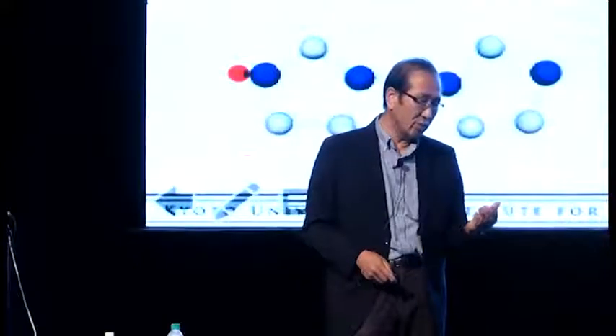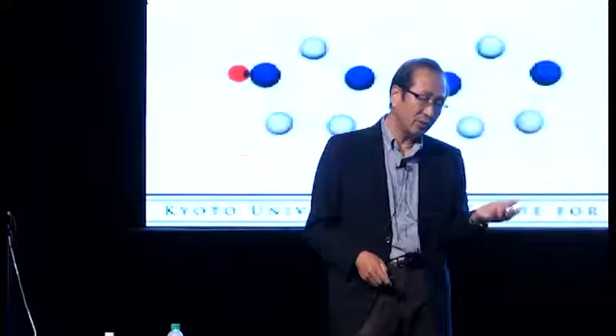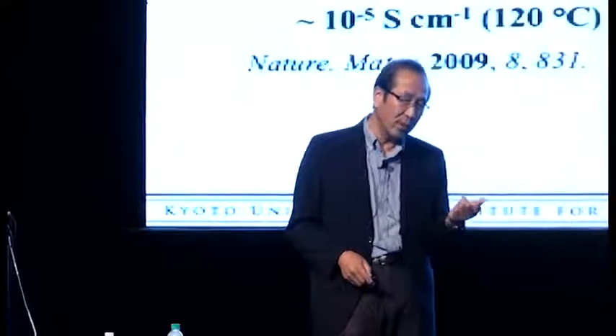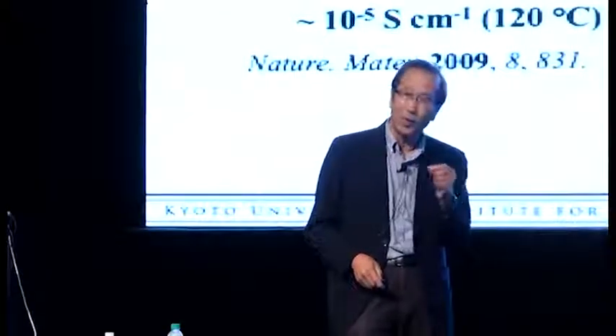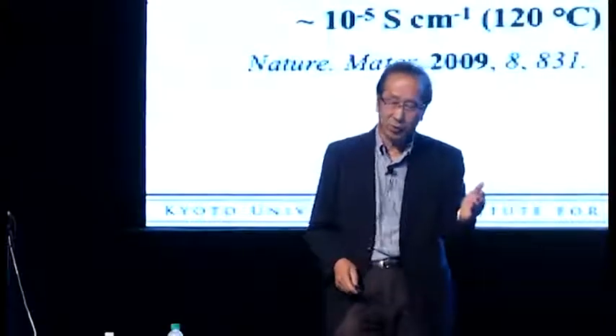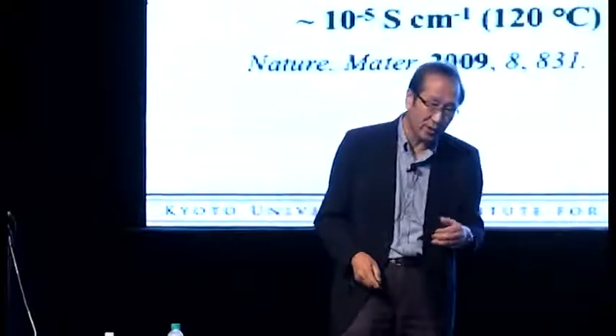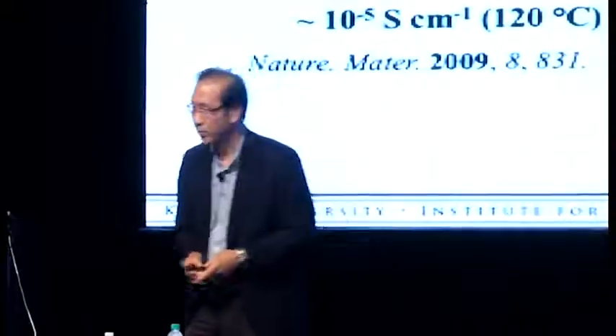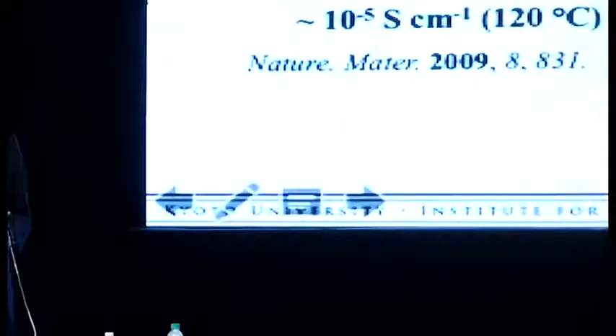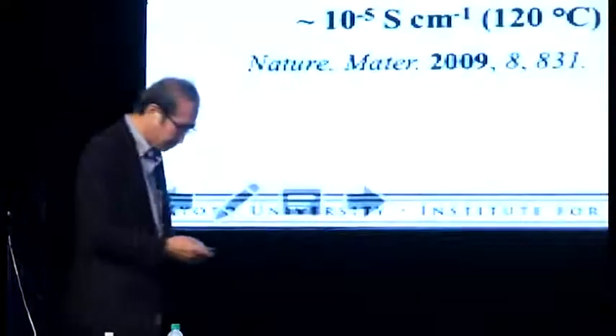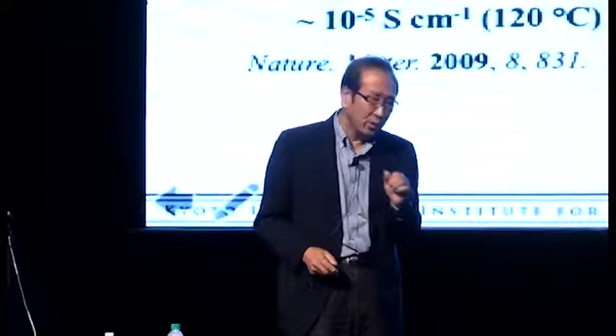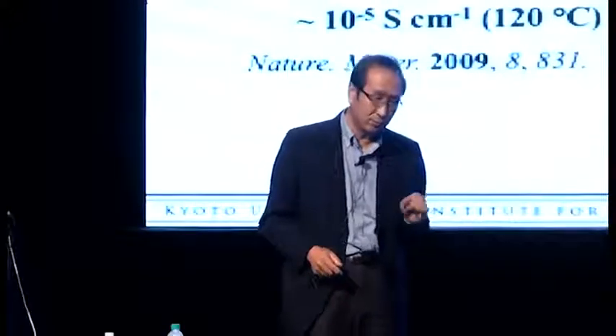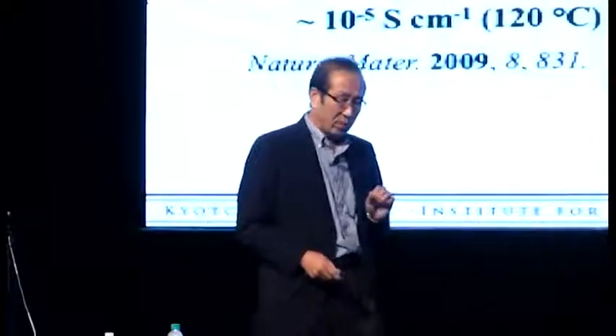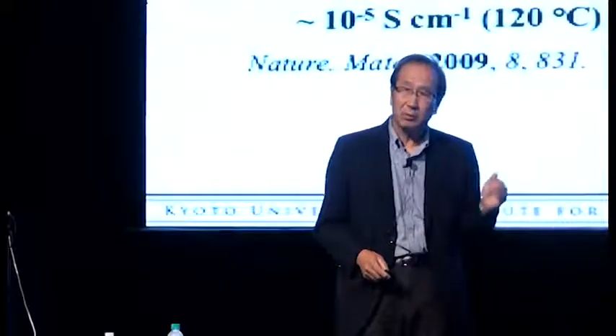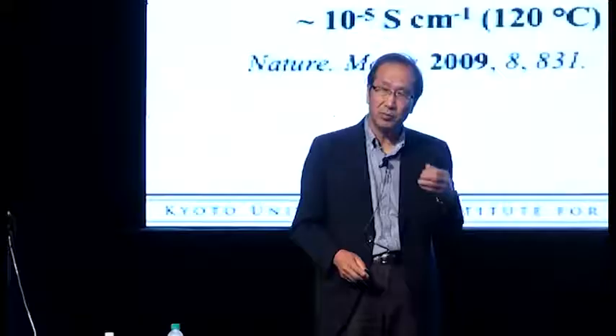Usually the proton is conducted using this type of water. But if we use this type of imidazole, for instance, we synthesize this type of materials, just incorporating the imidazole into the channels. Also, Professor Shimizu at the University of Calgary is synthesizing this type of material using triazole. The similar thing happens. Let me show you what's happening in this case. By sublimation method, we can introduce the imidazole into the channels. By heating, the imidazole rotates faster and faster. That means we can transfer proton from one imidazole to the others.